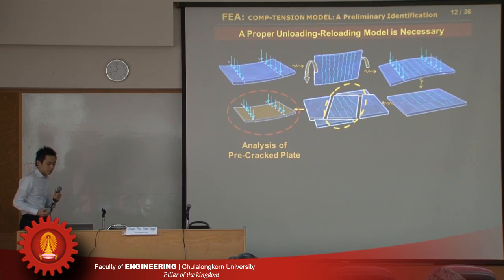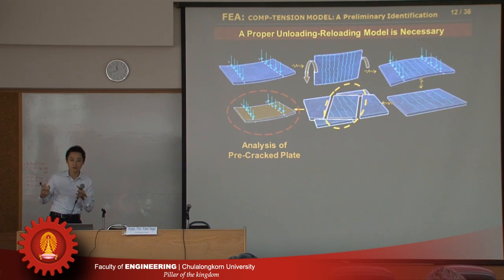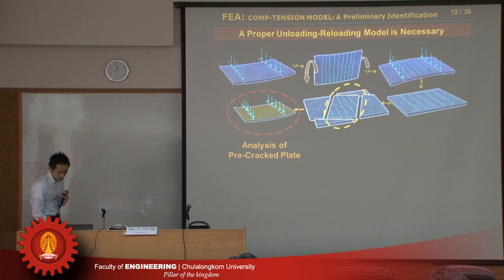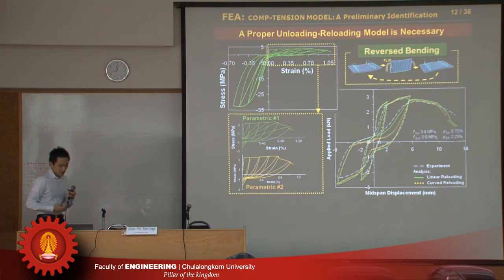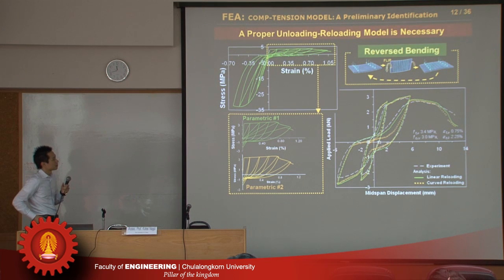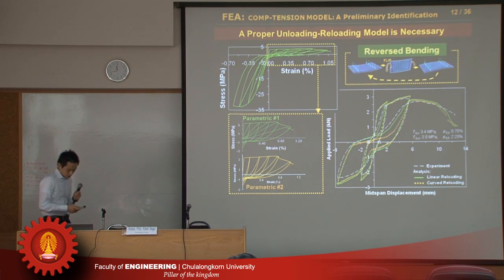So based on the compression and tension model newly developed, we checked this model's applicability or accuracy. Firstly, we check the unloading and reloading curve. To check that, we did the additional plate test where we did cyclic loading on the plate. So apply the load, just flip, and apply the load from the other side, and we did that many times. Then we could get the unloading and reloading curve of the plate.